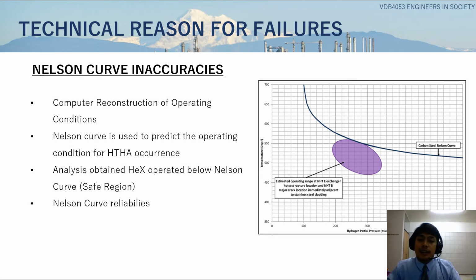Based on the data gathered, the heat exchanger was operated below the Nelson curve, which is a safe region, as you can observe in the diagram shown in the slide. However, hydrogen attack still occurred. This proves that the Nelson curve is not reliable to predict hydrogen attack as practiced by Tesoro Refinery. And thus, it needs a different approach to prevent hydrogen attack instead of solely depending on the Nelson curve, as its reliability can be questioned these days.